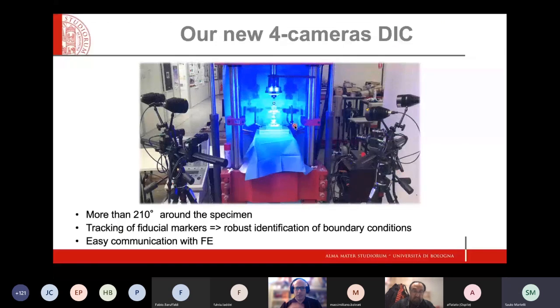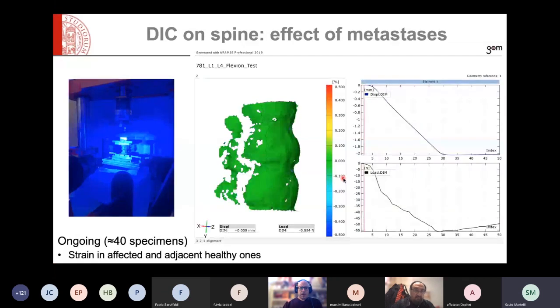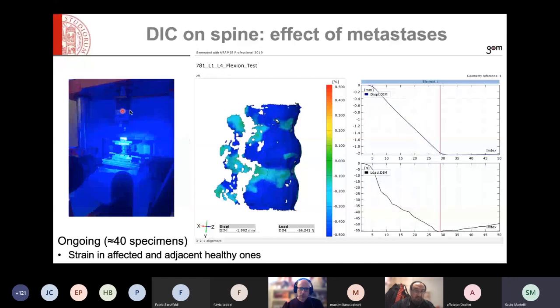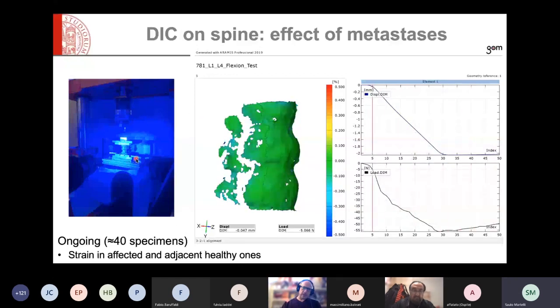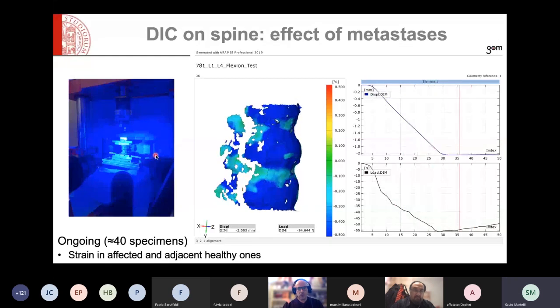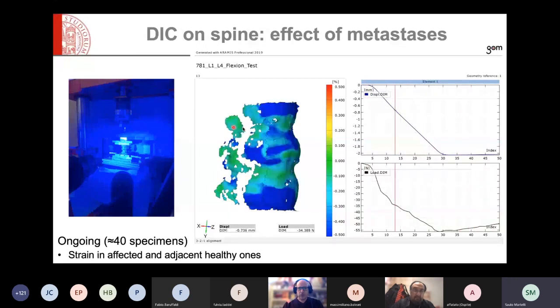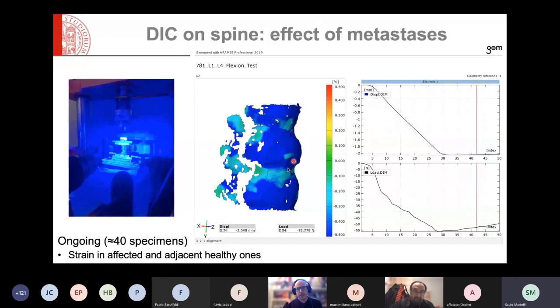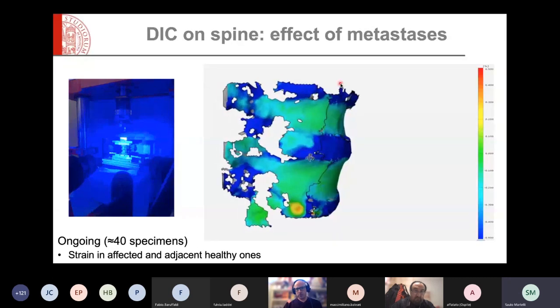This is the new system that we are using, which has 4 cameras and allows to observe the specimen all around, almost all around. It also incorporates a system for tracking fiducial markers, and this makes it much easier to interact between FE models and experiments. This is an ongoing research with Marco Palanca, where we are investigating metastasis on around 40 specimens. So this is how the deformation is changing in the healthy and affected vertebra when the load is applied. And thanks to the DIC system, we are able to watch what happens all around.